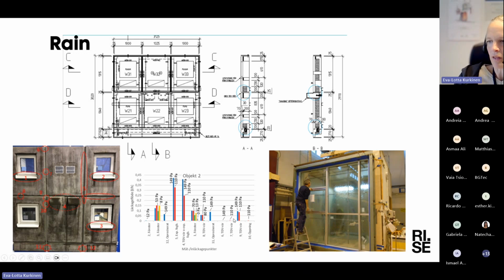All those staples with different colors show when it starts to leak rain. So the yellow ones are already between 0 and 10 Pascal. And we can see we have it for 2 of the windows. There is a rain leakage already at that low wind pressure. And it's wind pressure in combination with rain, I have to say. So this is just to highlight that you have to be careful with this, because it's very easy to have a leakage.